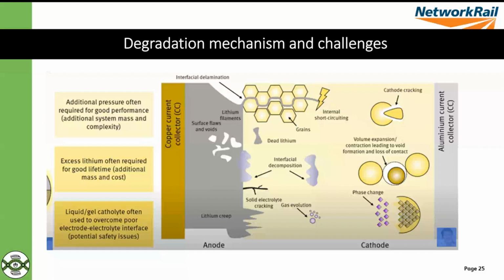Lithium metal is quite a soft metal, so you do get an issue of mechanical creep, which can cause short circuiting between the layers of the solid electrolyte, and also uneven loading of the anode, because of how ductile it is. You can get dead lithium forming within the electrolyte, so dead spots that reduce the performance of the battery. And because of this expansion and contraction, the electrolyte can become quite brittle, cracking, and then you end up with void formation as well, which is a key issue.